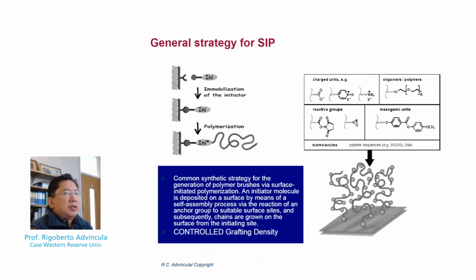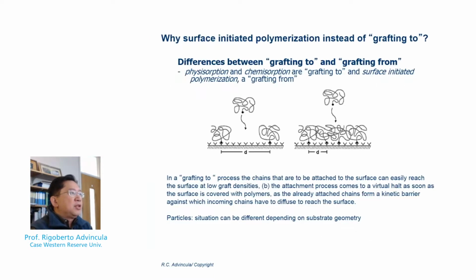So here's a general strategy for surface-initiated polymerization. The initiator is first immobilized on the surface. After immobilization of the initiator with a specific density, then polymerization takes place. Polymerization takes place where you have the active monomer diffusing to the surface. And then as the polymer grows, there's crowding out of the interface. And hence, one of the challenges of a grafting from technique is actually diffusion of the monomer and the crowding out of the interface or surface, hence sometimes leading to inefficiency or non-initiation of the surface-bound initiators.